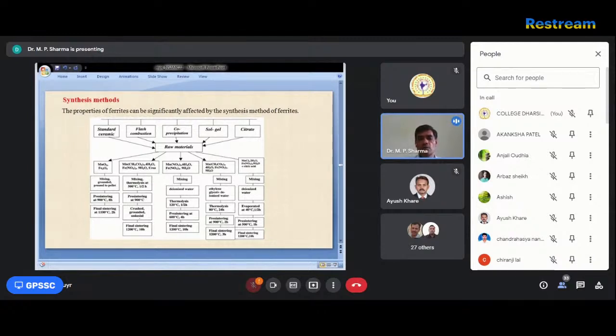Now another is the co-precipitation method. It is also similar to the sol-gel. It is the simplest and a convenient method to synthesize magnetic particles. In this method, a uniform composition is obtained by the precipitation reaction of two or more cations. This involves four steps: nucleation, growth, coarsening, and agglomeration.